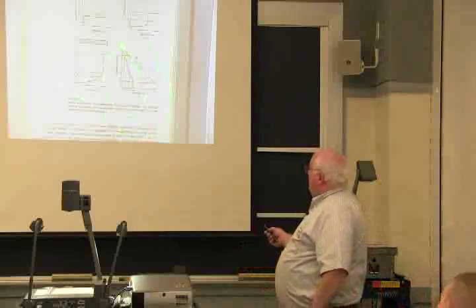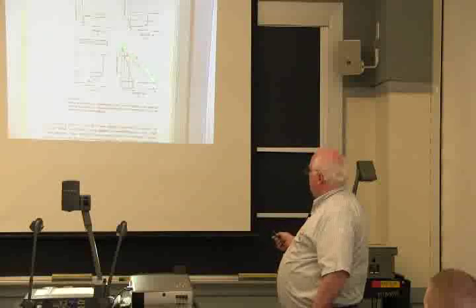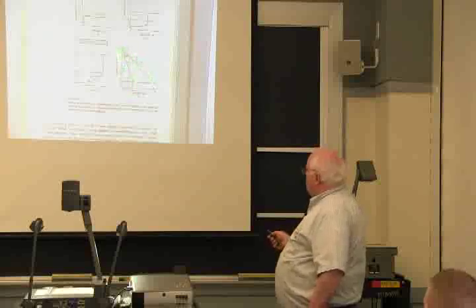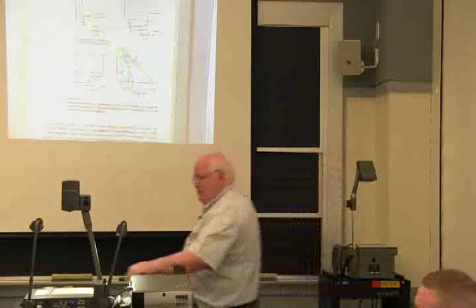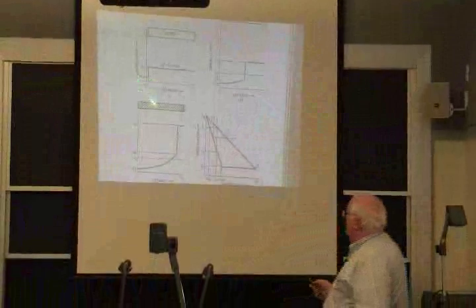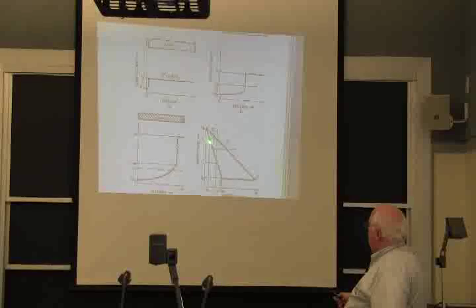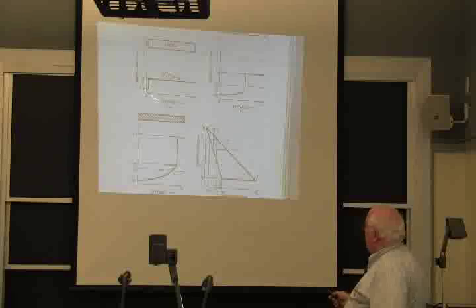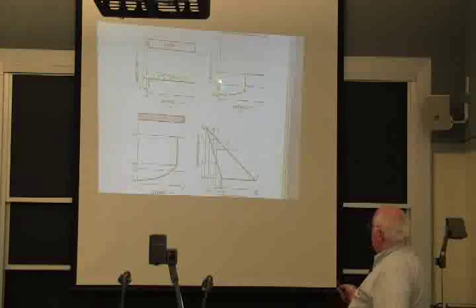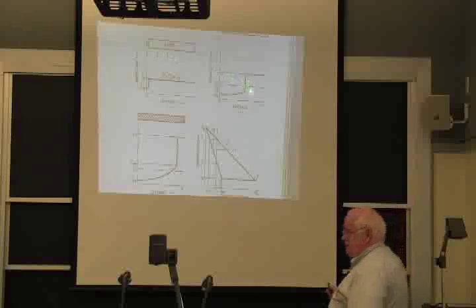In any case, you have a liquidus line, you have a solidus line, and the solidification folks like to describe that in terms of a partition coefficient, K, which is just the composition of the solid over the liquid. So the first solid to form will be K times C0, where C0 is the average composition of your melt.